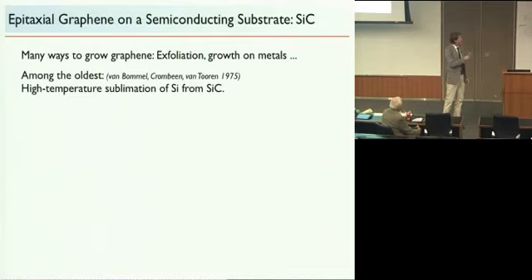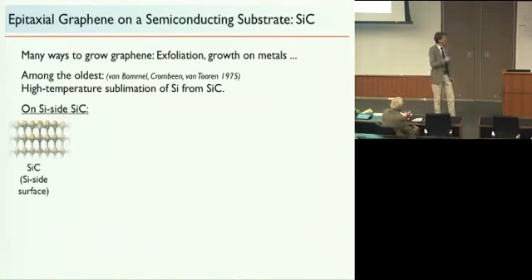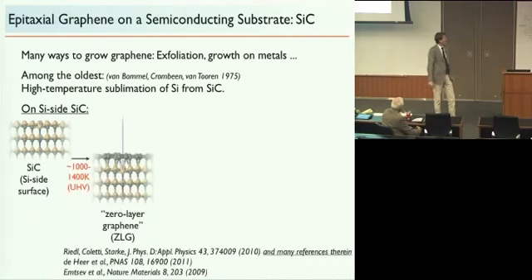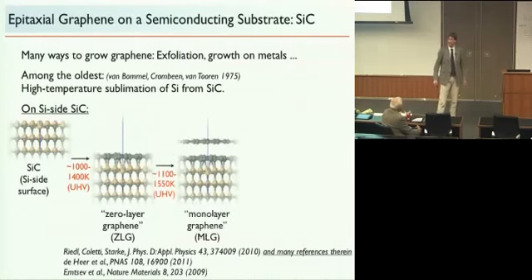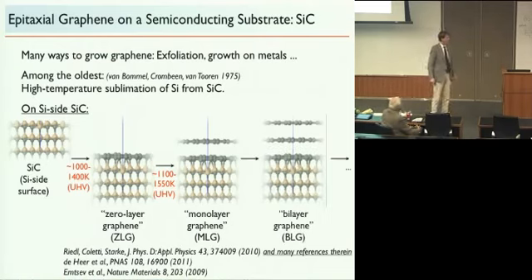There are many ways to grow graphene, but this is actually one of the oldest that I showed you here, the high temperature sublimation of silicon. Basically, you prepare your silicon carbide surface, and then you evaporate away the first three planes of silicon here by heating. You leave behind the carbon atoms, and what you get is a structure that looks like this. This up here is carbon atoms. It's not yet graphene, in fact, because it's covalently bonded to the substrate. But if you heat a little bit more, this layer lifts off. The next layer of silicon atoms evaporates somehow, and you get the same interface, but underneath a graphene plane, and so on, or bilayer, and so on.